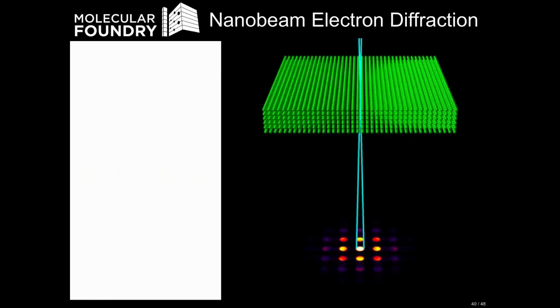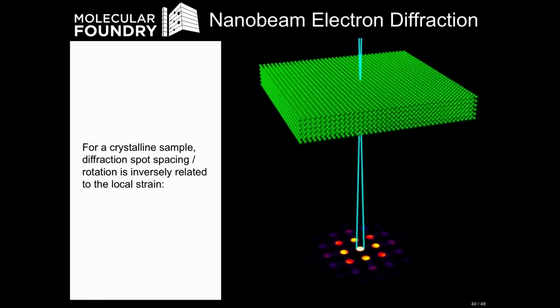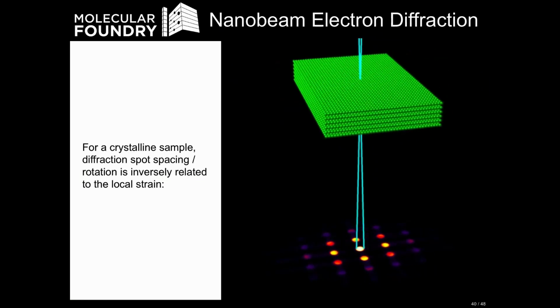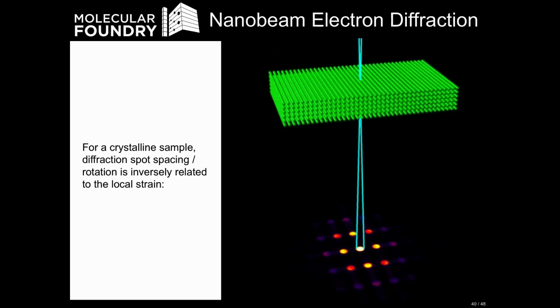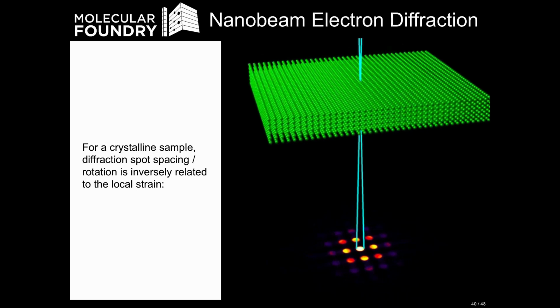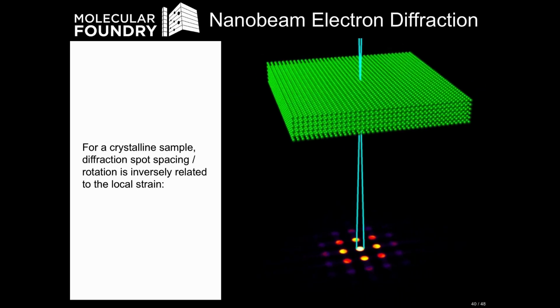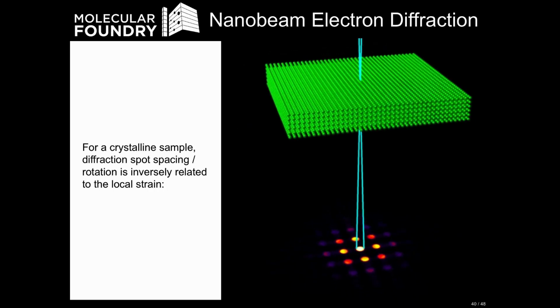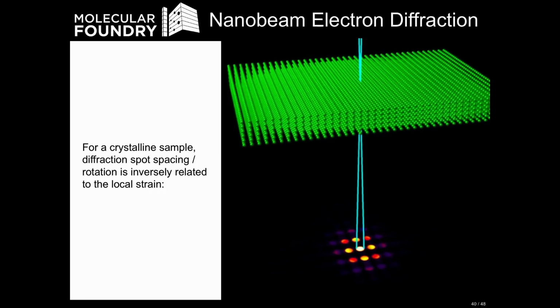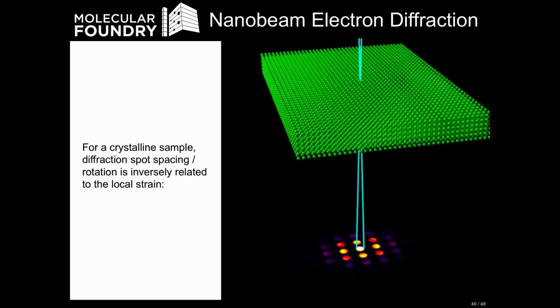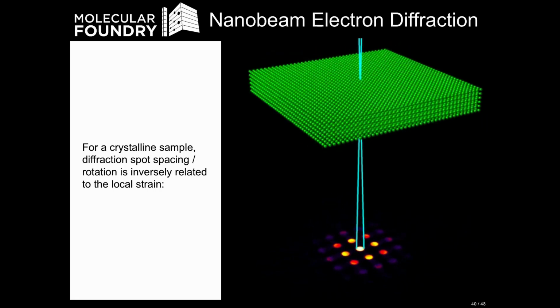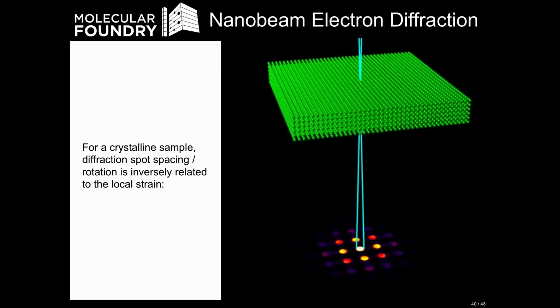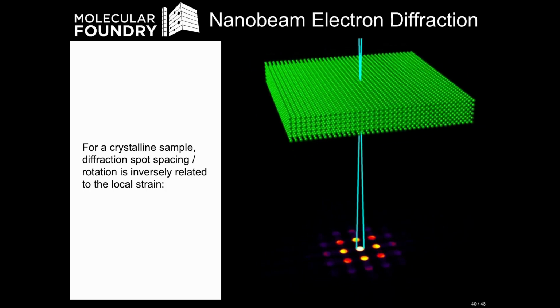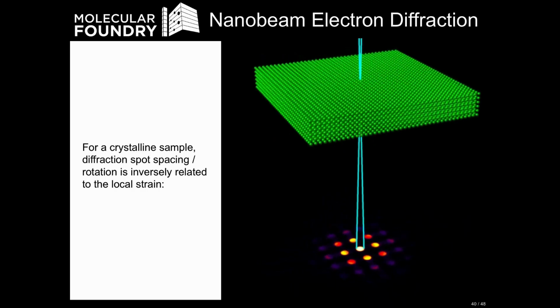So the geometry of this experiment for nanobeam electron diffraction, for NBED, looks very simple. You tilt your sample to a zone axis, and this movie shows how, if the lattice spacing changes in the directions perpendicular to the beam, you get expansion or contraction of your lattice spots. So if your sample's in tension along a given axis, your spots move closer together, and if it's in compression, they move further apart. It's just an inverse image of the lattice vectors here. And so all we need to do is some kind of template matching or correlation or convolution, whatever you want to call it, and measure the disk positions. And if we can measure them with high accuracy, we can measure the strain.